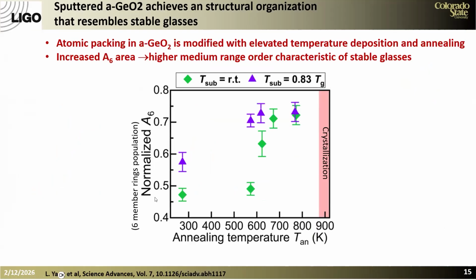So here I am plotting the normalized area A6. This is the area of the 6-member rings as a function of the substrate temperature. These are the green diamonds, and purple squares, and also as a function of annealing. And what you see here is that the predictions of the model agree with the experiment, because when we grow near the glass transition temperature, we actually obtain a more stable glass-like material. And then when we grow at room temperature.